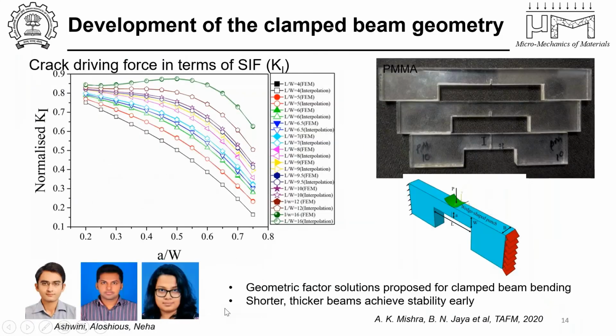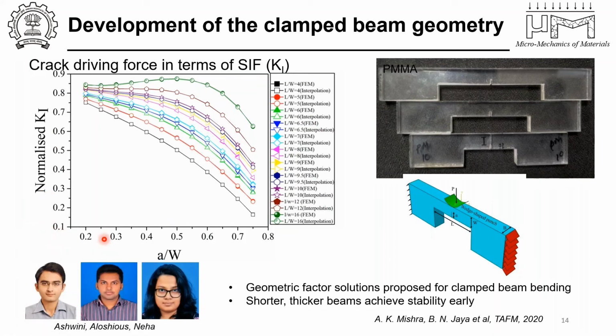So we evaluated the normalized stress intensity factor, which is nothing but the geometric factor that I was talking about earlier as well, for different a/W's and for different L/W ratios. When I say L/W, it's the length to width of the specimen. So in the future, I would call this the beam aspect ratio. So this is the relative crack depth, and this is the beam aspect ratio.